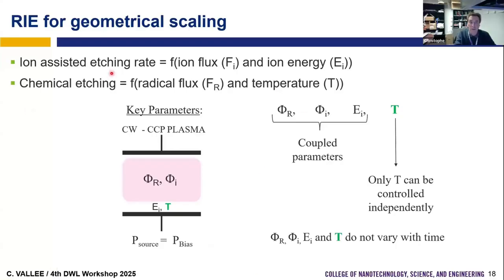When we had the very first generation of plasma etching reactor, I will say the single frequency CCP plasma reactor, you apply a power with a single generator. With this power, you will fix the plasma density, so you will fix the ion flux and the radical flux. Usually the temperature is fixed. And depending on the power you apply, you will also fix the DC self bias, so you fix the ion energy.